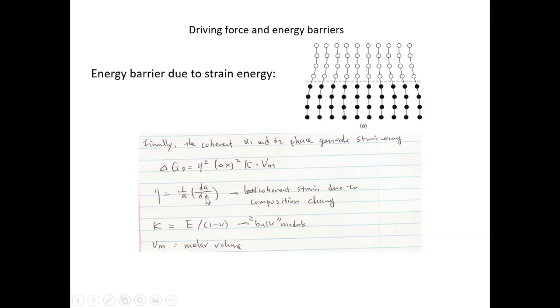So suppose the lattice here is A, and this is changed a little bit. If you go through this region to this region, you have a change of the lattice. We're writing down the change of the lattice parameter as a function of composition. If your composition varies a little bit from this region to that region, you have a slight change of the lattice parameter, and you get a strain here. For the same consideration, we write down the strain energy as a quadratic form. This is kind of a spring constant, and this is very much like the displacement of the spring. Altogether you have another contribution, the strain energy for the system. So this is another source of barrier that you build into this because it's a solid phase transformation.